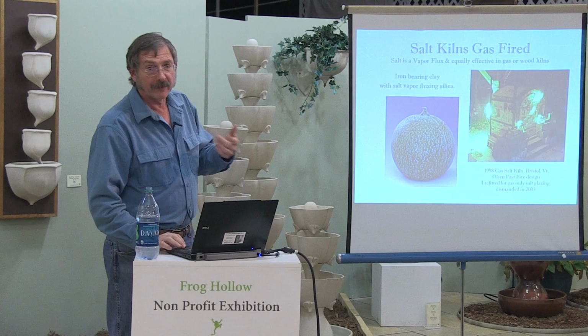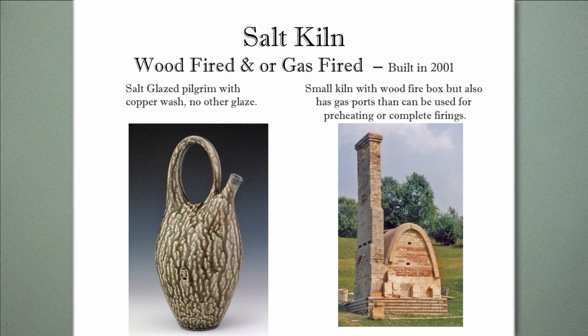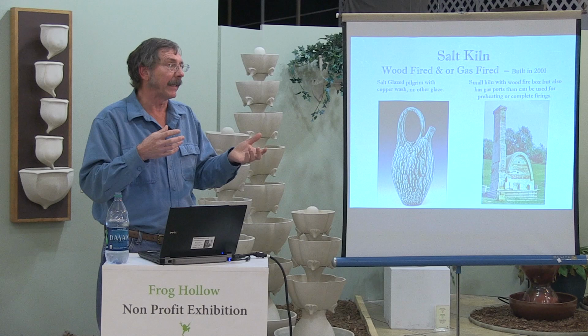And then I eventually moved on to a much more appropriate salt kiln, which is really a test kiln for me. This is up the hill from my larger wood kiln. It's big enough that I can fire 40, 50, 60 pots at a time and test out ideas in salt: how much salt to put in, where to stack the pots. I'm using a lot of washes these days. I try not to put glazes on too many of the salt pots I fire.